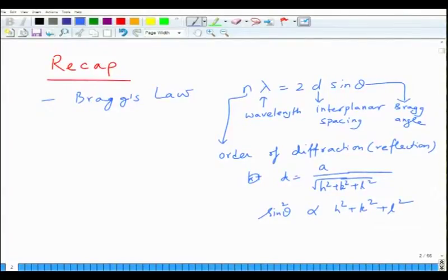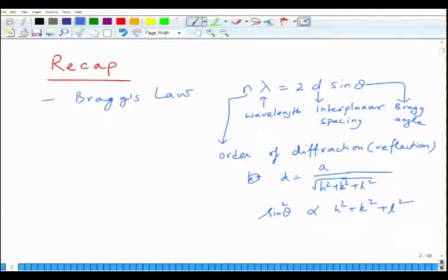In most cases, at least for powder diffraction, we take lambda to be constant, and n is the order of diffraction, which basically means that if you have a diffracting peak for the 100 plane at say theta 1, then the 200 plane will diffract, whether imaginary or not, at an angle theta 2, which is higher than theta 1, because the 200 planar spacing is half of 100.